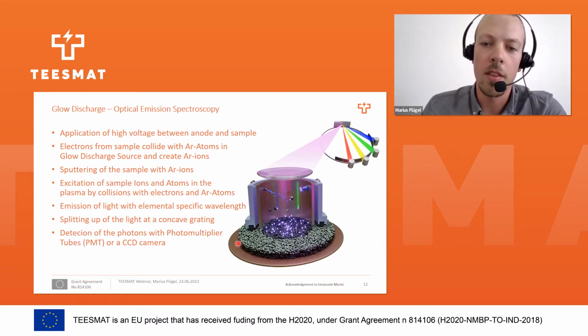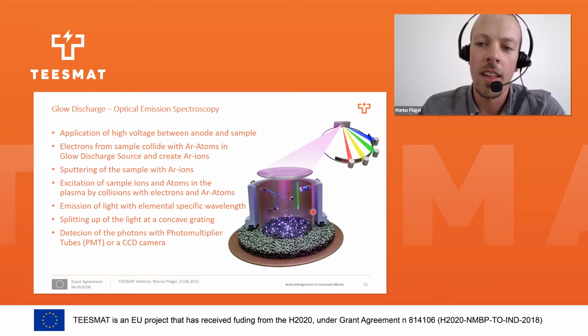Our sample that we want to investigate is put into electrical contact with our GD-OES cathode. It's placed right under the GD-OES anode, which can be seen here as a half circle. And this is just a cross section. The real GD-OES anode is completely round. And the plasma chamber is sealed by the sealing ring. The plasma chamber is then evacuated and filled with argon gas.